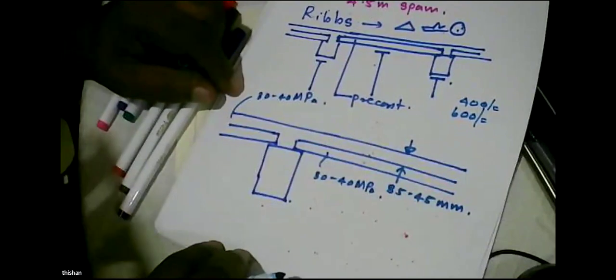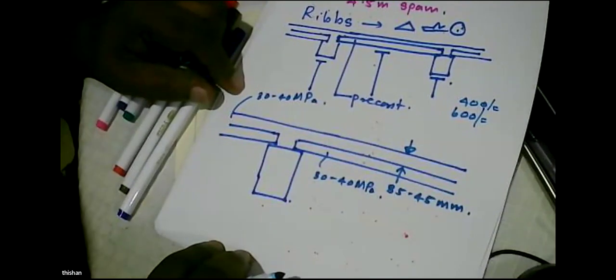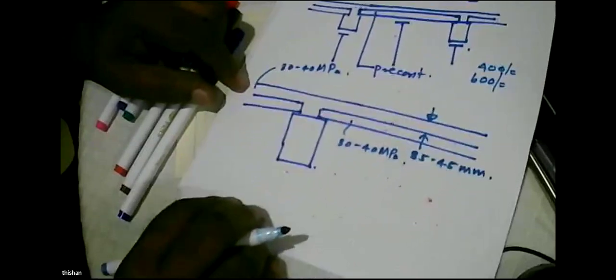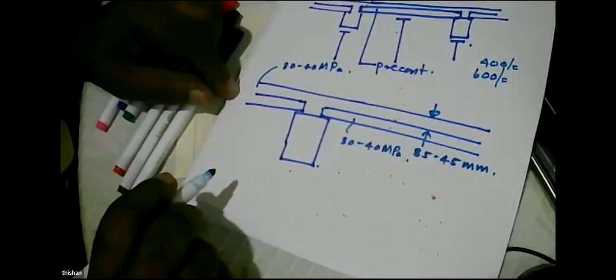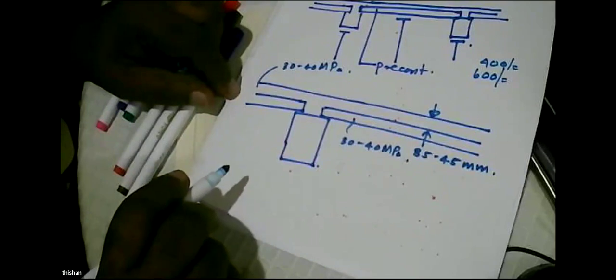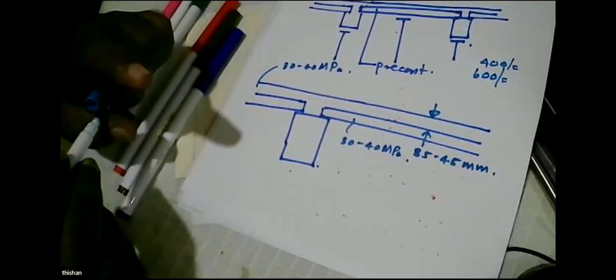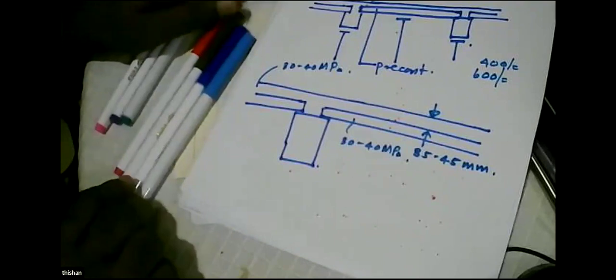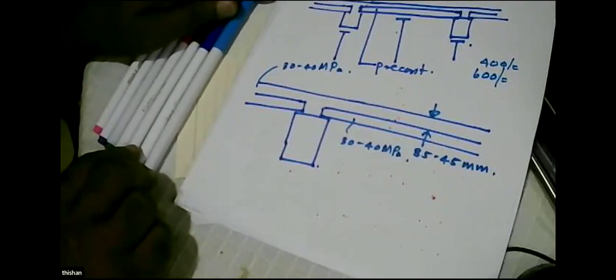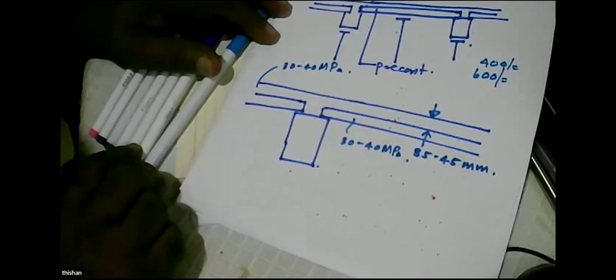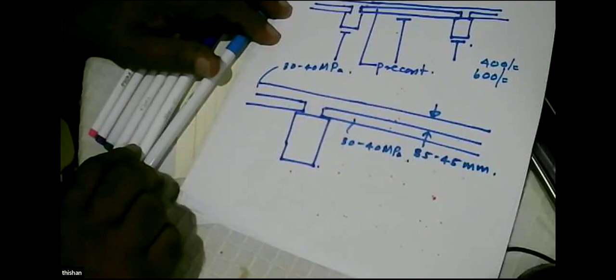Because the higher the strength, the lesser the cover required, because we are going for thin construction. If you are going for thin construction, we know in concrete, cement is the friend, what is the enemy? So reduce the enemy by using admixtures, so that with the same amount of cement you can get high strengths, like 30 to 40 megapascal. And once you go for 40 or 45 megapascal concrete, the ingredients are the same, but the durability is very high. We can reduce the cover requirements.